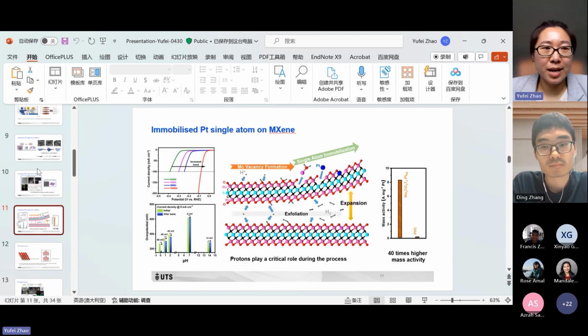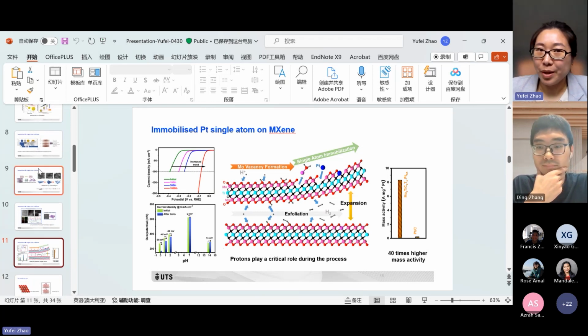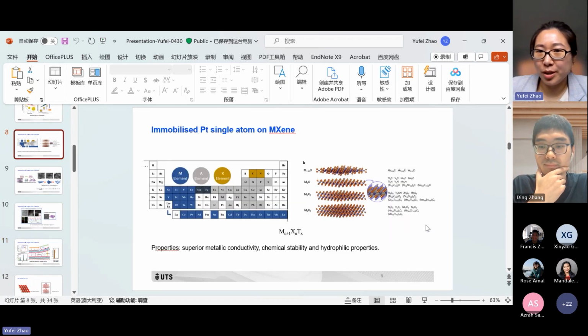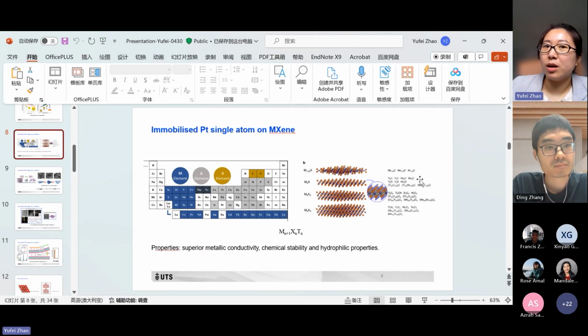And for MXene, I think if we want to develop some electrocatalyst for acidic conditions by utilizing MXene, we actually have a lot of choices, especially the molybdenum or tungsten-based MXene. We can choose to utilize it as the substrate to support our single atoms or atomic clusters because it's quite stable in acidic conditions.